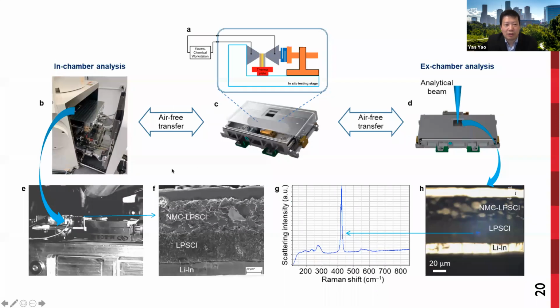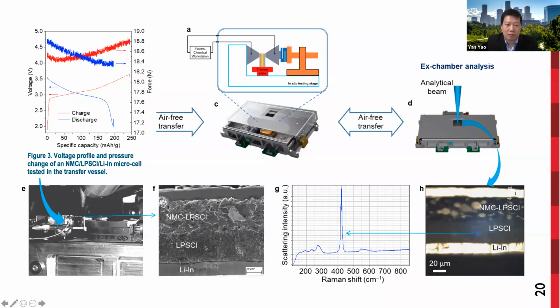This slide shows an example of SEM observation of a cross-section of the thin cell mounted on the platform. The SEM shows a cross-section of the tri-layer structure of cathode, NMC, and the electrolyte layer, and this anode lithium-indium layer. So we can also perform Raman spectroscopy on the same thin cell and the same area.